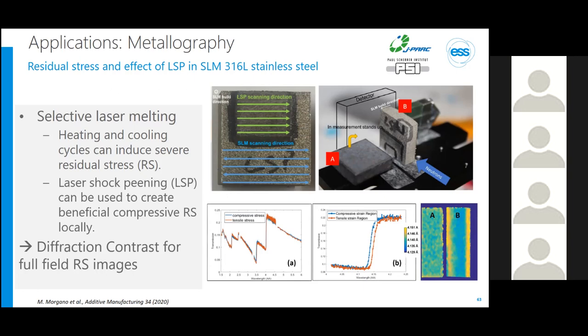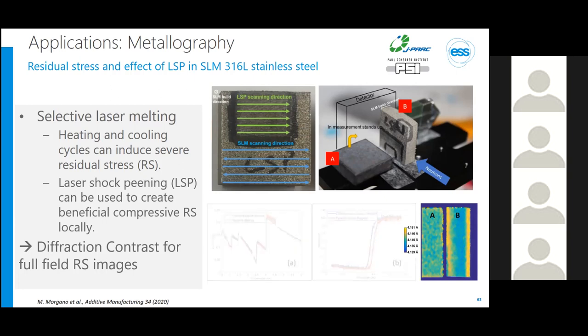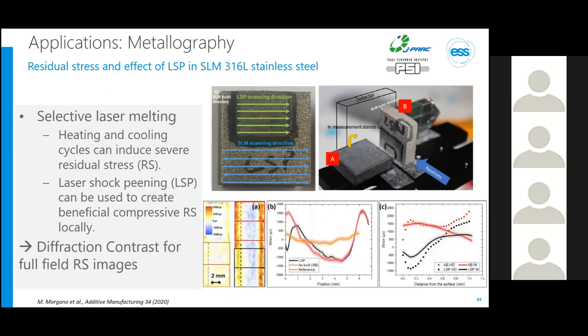We obtained the spectra with very nice Bragg edges, and we determined the position for every pixel. These images can then be used to evaluate the strain distribution and how it changed due to the laser shock peening process, allowing us to optimize the process parameters. So you have a quick method to access what you have done beforehand.